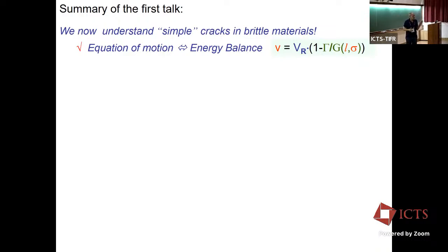One funny part about this equation of motion, which is very strange for physicists or for anybody actually, is that V instantaneously depends on all of these things. There's no V dot. There's no time derivative of V here, so there's no acceleration dependence. If gamma will change like a step function, according to this, V will jump immediately as well. We'll see that actually happens. For large systems, V has no inertia. It behaves like a massless entity, or the crack behaves like a massless entity.